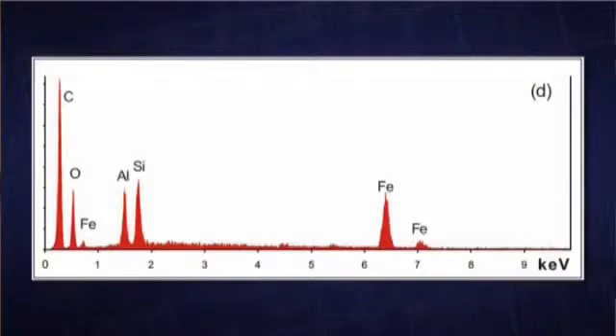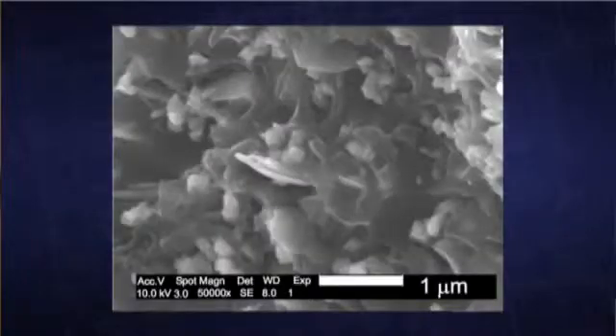The primary elements in the red material are aluminum, iron oxide, as well as silicon and carbon. The iron oxide appears in faceted grains, approximately 100 nanometers across. The aluminum appears in thin platelets, about 40 nanometers thick. It is the small size of the particles involved in this material that allows us to characterize it as nanothermite. In ordinary thermite, the particle size is much larger, and hence ordinary thermite is an incendiary, whereas as the particle size becomes smaller and smaller, it can become explosive. Super thermite is sometimes called.